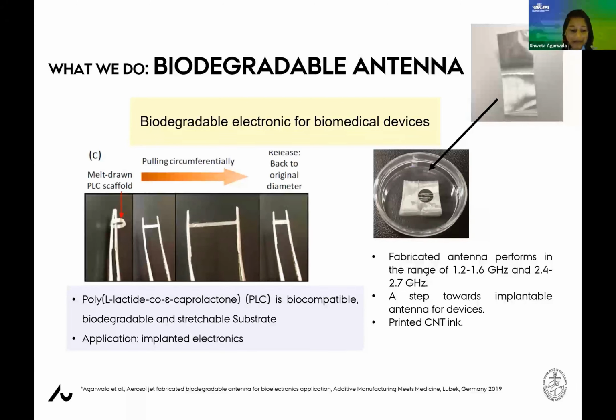The final investigation was that if I were to put this whole printed PLC material into the same environment as a human body, which is 37 degrees centigrade with a certain amount of oxygen and carbon dioxide, what happens to it? And we found out that within 1.5 to 2 months, everything completely degrades. There's nothing left.